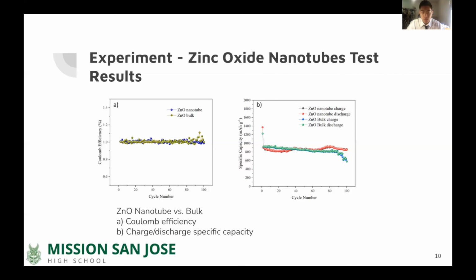After this initial drop, the zinc oxide nanotubes consistently outperform the bulk due to their greater stability and smaller volume expansion. This can be seen by comparing the reversible capacities, which is found by dividing the discharging specific capacity of the last cycle by the specific charging capacity of the second cycle. These values are 93.74% for the nanotubes and 62.73% for the bulk, showing that the specific capacity of the bulk drops significantly after many cycles. This can also be seen by looking at the variation in the Coulomb efficiency, which is the gray line. There's a much greater fluctuation of Coulomb efficiency in the bulk, while it's fairly flat for the nanotubes.